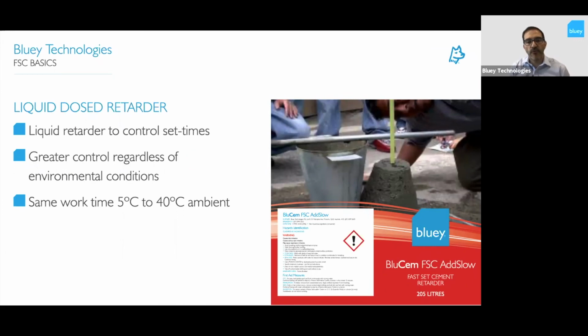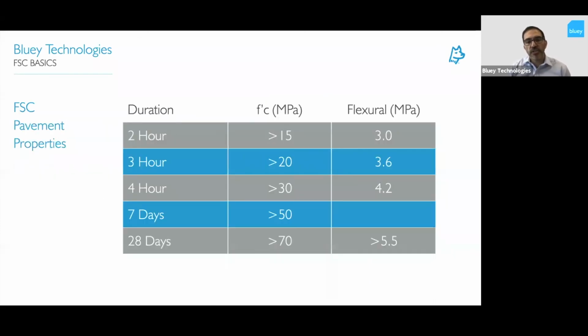So we can now modify the set time on the product to suit the ambient conditions, which has made a really big change to the way we use fast set products. Just a summary of the properties that we achieve in terms of compressive strength and flexural strength at the different times, just in this table here.